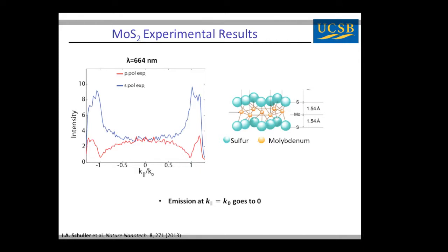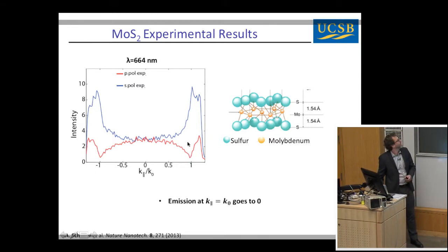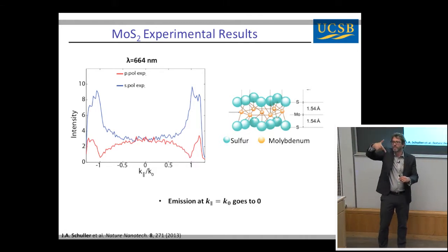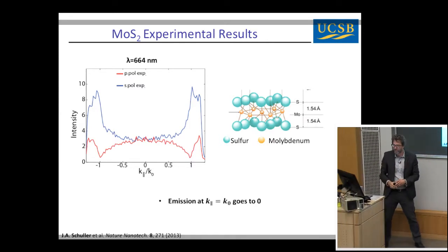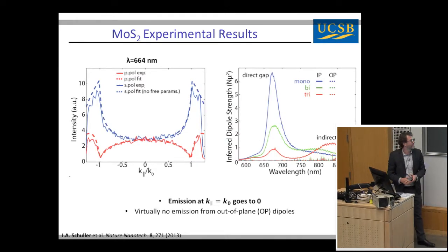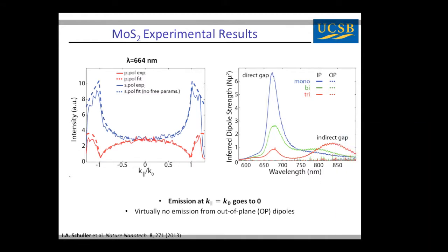When we look at, let's say, a monolayer of MoS2, at every wavelength, we get a plot of the PL intensity as a function of the emission angle. Okay? So now I'm showing you from -1 to 1, or a little bit larger range. Red is p-polarized light. Okay? P-polarized light comes from a combination of in-plane and out-of-plane dipoles. The blue is s-polarized light, which only comes from in-plane dipoles. Okay? So these are experiments, and what we did was fit our p-polarized data to determine how much of the light is coming from in-plane dipoles and how much from out-of-plane dipoles. Okay? And in doing so, we generate a parameter-free independent fit of the s-polarized data. Okay? So the key feature here is, if you remember the calculations I showed, our dip goes basically to 0 at the critical angle, which is a signature that we have only in-plane dipoles in our material. Okay? So the blue curve here is what we get from a monolayer.